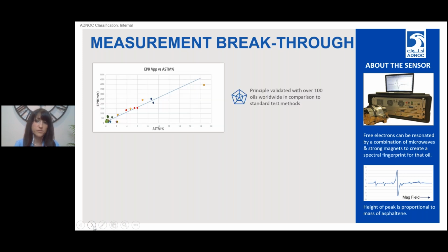But of course, before we go in to fabricate the device, we had to do a lot of measurements or verifications in the lab to ensure that using EPR, electron paramagnetic resonance, when we measure the concentration of asphaltene, is equivalent to our standard methods that we use in the lab, you know, the wet chemistry methods. And we did look at 100 samples from across the world from different oils, and this is correlated.